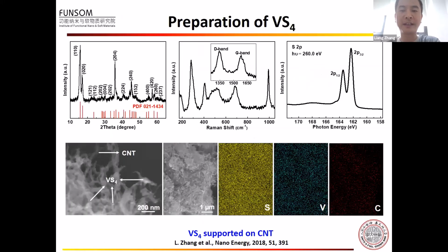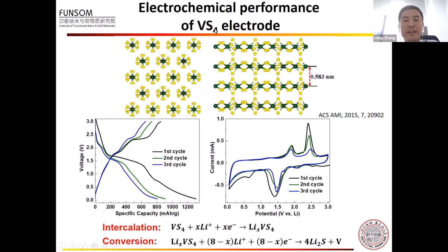For the moly sulfide, it has 2 sulfur in each unit. If we increase the content of the sulfur in the unit, in principle, we can increase the capacity. Therefore, we designed the material VS4 and investigated the reaction mechanism, and the XPS, XRD results and SEM indicate the successful preparation of this material. Different from moly sulfide, VS4 has a linear structure with a chain distance of 0.58 nanometer, and it also has two reactions during the lithiation. One is the intercalation reaction, and one is a conversion reaction.